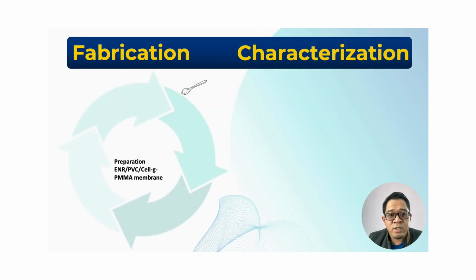The fabrication of the thin film. The thin film manufacturing process consists of two main stages. First, matrix preparation and thin film molding. The ENR PVC is prepared using a solution mixing process. Epoxidized natural rubber is dissolved in tetrahydrofuran to produce a homogeneous solution.